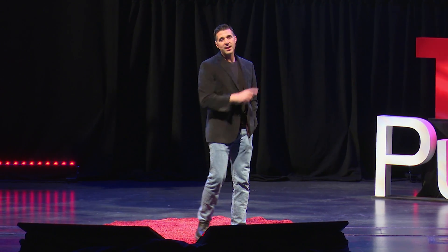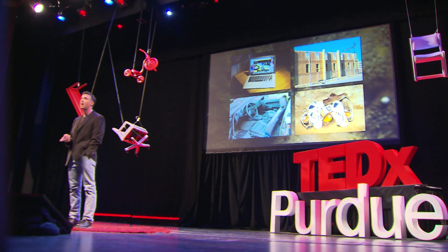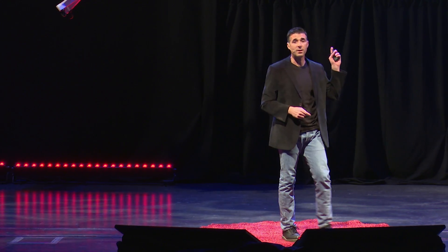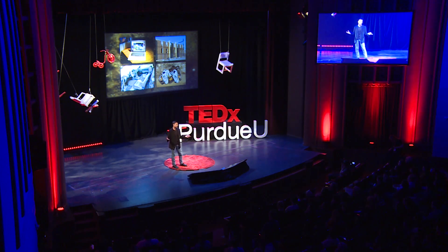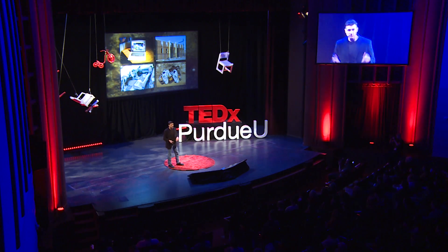So what do we want to do with these things? Think about products you're really familiar with — your cell phone, your laptop, plywood in most structures, the interior of your car, shoes, phone books. They're all held together with adhesives. There are two main problems with the adhesives used in these materials. First, they're toxic: the worst offender is plywood, furniture, and wood laminate flooring, where the main component is formaldehyde — a gas and a carcinogen. We're constructing a lot of structures from these adhesives and breathing this carcinogen. The other issue is that these adhesives are all permanent — so what do you do with your shoes, car, or laptop at end of life? For the most part, they end up in landfills. There are precious materials in there we'd love to recycle, but we can't because they're all stuck together permanently.